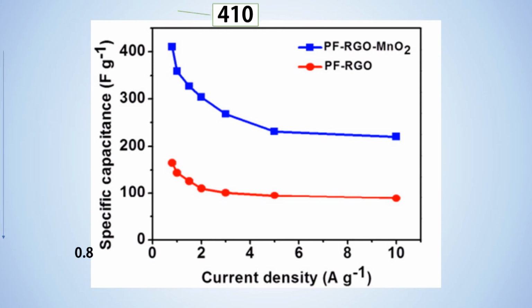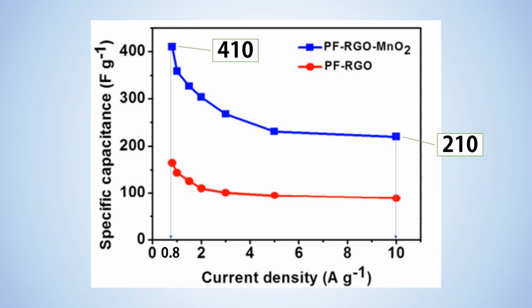The specific capacitance of the PFRGO MnO2 electrode is up to 410 farad per gram at a current density of 0.8 ampere per gram. And even at a discharge current density of 10 ampere per gram, the specific capacitance is still as high as 210.